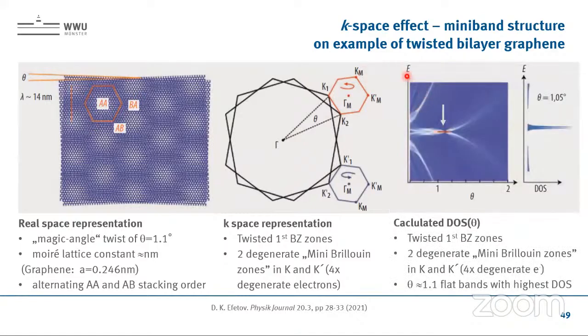And with that you get an energetics here as a function of the twist angle, because with the twist angle you can adjust the length, the wavelength, the lattice constant, so to say, of this moiré potential. And with that you dramatically change, let's say, the energetics, and the color code here is the density of states, which is plotted again here, energy versus density of states. And you see that's graphene, so that's the Dirac part. And here in the middle, something new happens. You have these huge flat bands with a high density of states.